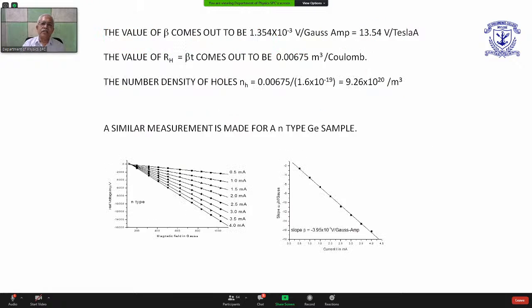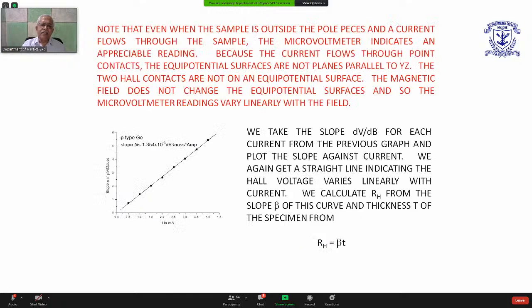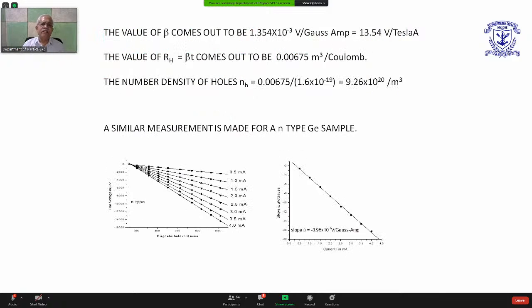Now, the previous data is actually measured data, and that data yielded a value of beta to be something like 1.354 times 10 to the minus 3 volt per Gauss ampere. Using this value, RH is computed as beta times T, where we know T, the thickness of the crystal. It turns out to be something like 0.00675 meter cube per coulomb.